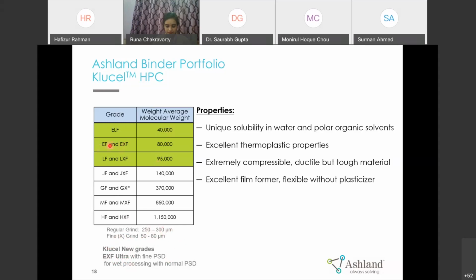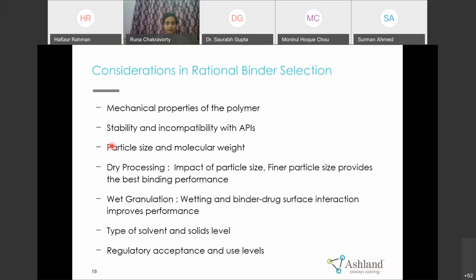So when should we use the regular grade and when should we use the finer grade? Whenever you are using a dry binder, either doing dry granulation, direct compression, or wet granulation where you add the binder in the dry mix and granulate with water, particle size is very important and you can use the finer grade. But if you are making a binder solution and granulating with it, because you are going to dissolve it, particle size is not important when it comes to product performance. There you can use regular grades like EF or LF. So these are the considerations you need to concentrate on before selecting any binder for your tablet formulation.